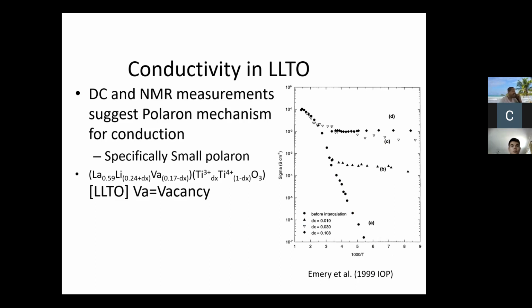But in terms of trying to understand this conduction mechanism, there's a study done by Emery et al. in 1999, where they did DC measurements. In order to calculate the electronic conductivity, you have to find a way to suppress or stop the ions. The way to do that is to run DC measurements by blocking the solid electrolyte with gold electrodes, so lithium can't transport through. When you run a current through it, the lithiums get stopped, so the only things that can transport are holes and electrons. Through this way, you can get the electronic conductivity.